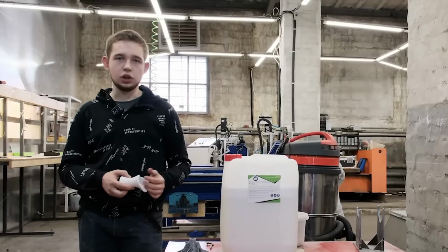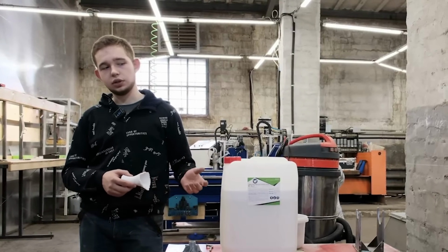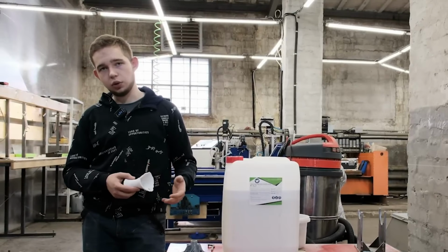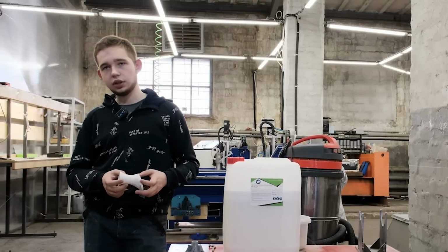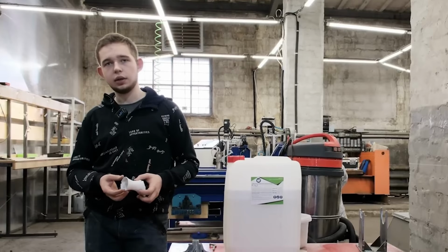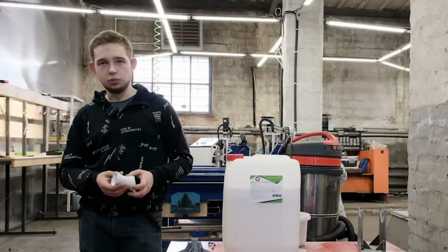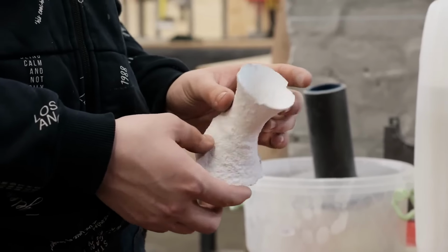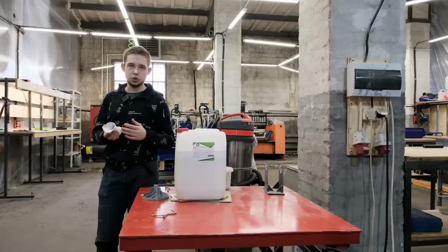Afterwards, the mold is carefully calcined, which means that first, the original model is either melted out or burned out. Then, the mold itself is calcined. And finally, the molten metal is poured into the prepared mold. As you can see, this mold is cracked. This is the part where the sprue was.